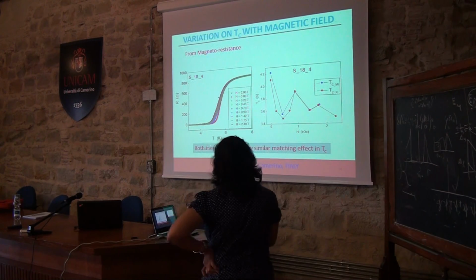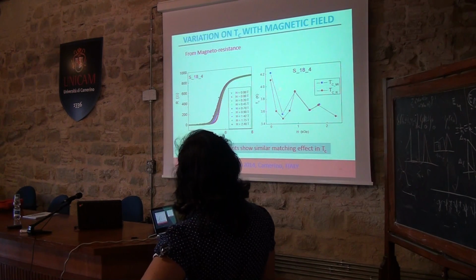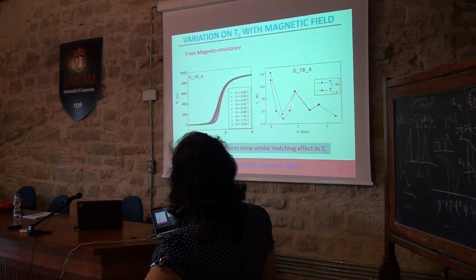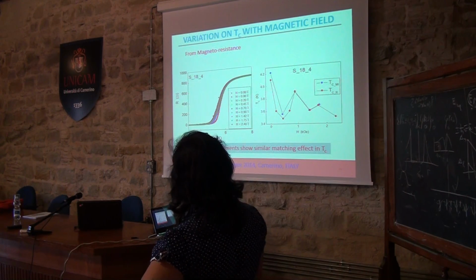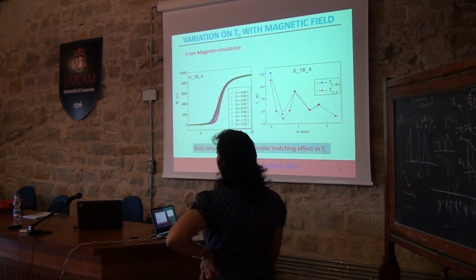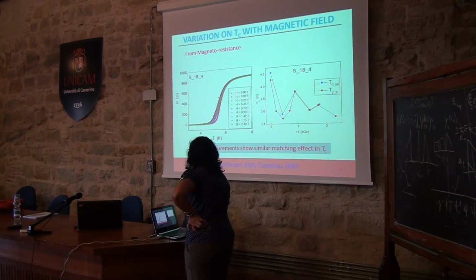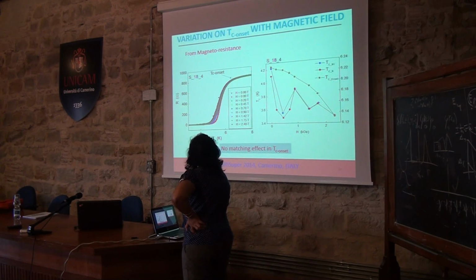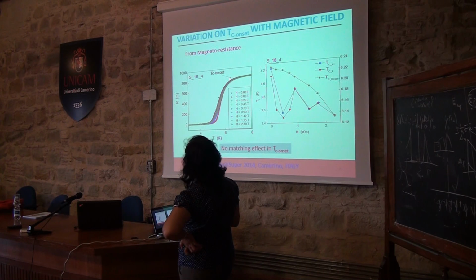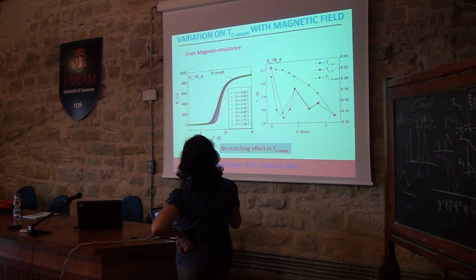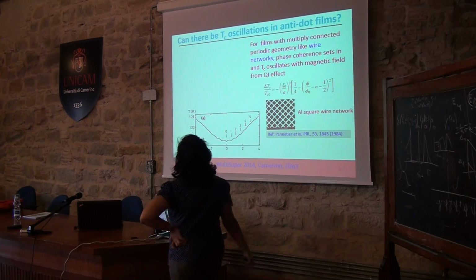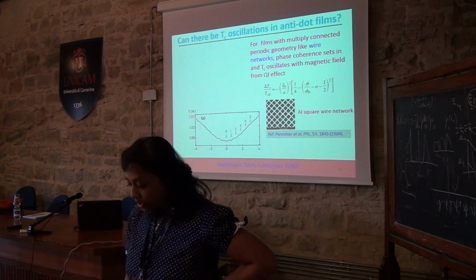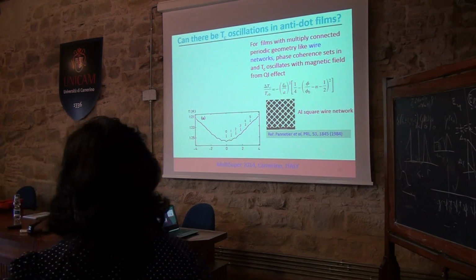We also matched it with our magnetoresistance measurement, and here you see the blue one is from mutual inductance, the red one is from magnetoresistance, and we indeed see an oscillation in Tc. However, the Tc onset was not showing any periodic variations. So now, can there be Tc oscillations in an antidot film?